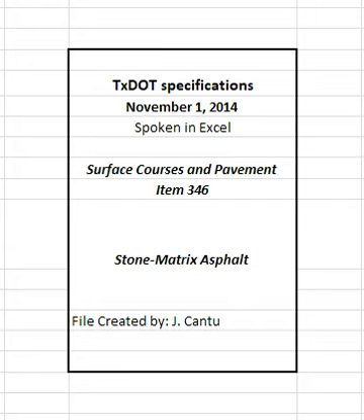4.4.2.1.6 Ignition oven correction factors. Determine the aggregate and asphalt correction factors from the ignition oven in accordance with TxDOT 236F. Note that the asphalt content correction factor takes into account the percent fibers in the mixture so that the fibers are excluded from the binder content determination.